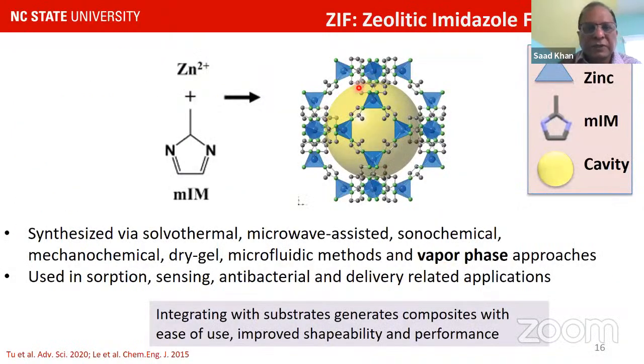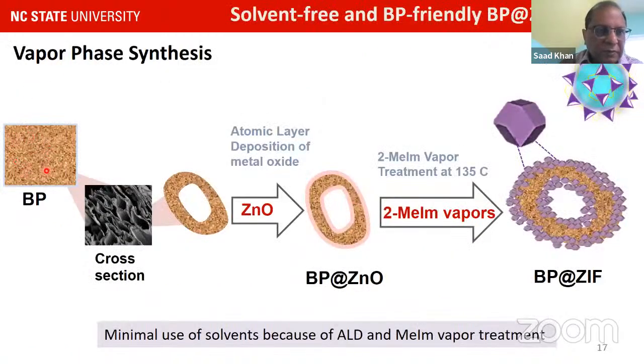The MOF we have used is ZIF, and there are many ways of adding MOF. We have used the vapor phase approach, although there are many other approaches. The way we have done this is the following. We take our banana papers, the same banana paper which is helping us improve crop yield in Africa. This is the cross section. We do atomic layer deposition on it with zinc oxide. And then we put some vapor of the MOF precursor at a certain temperature, and out comes the banana paper with the MOF impregnated in it. So it's a vapor-based treatment, although there are other approaches that can be done.